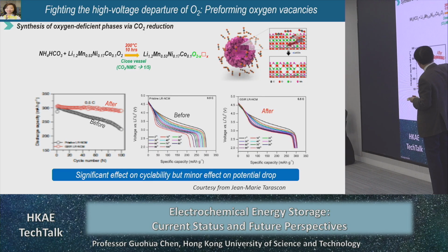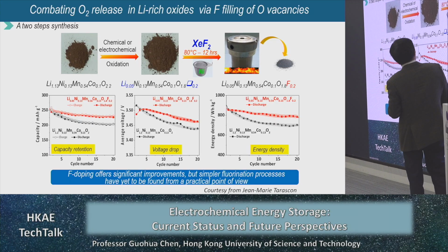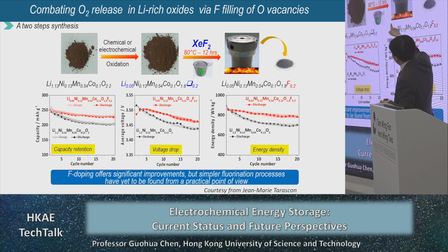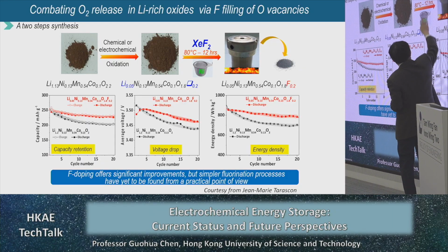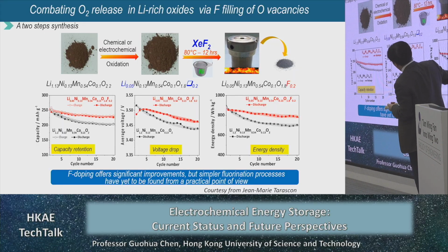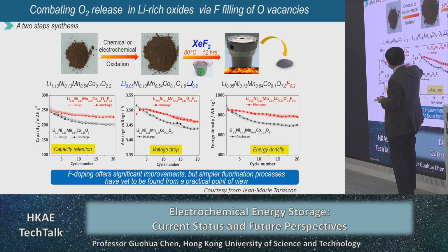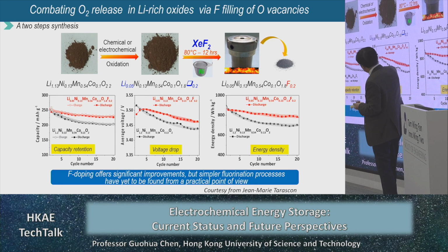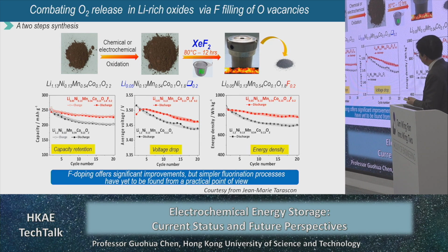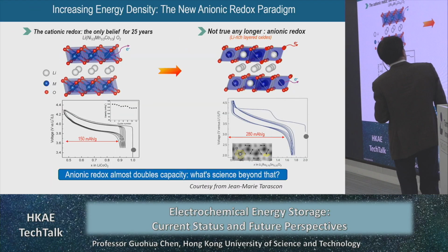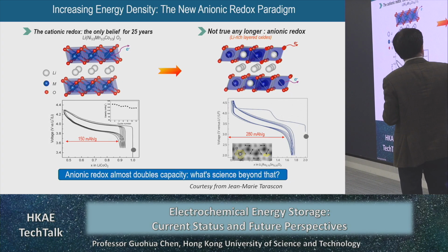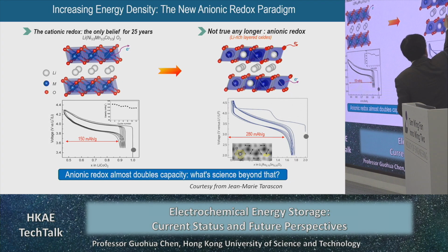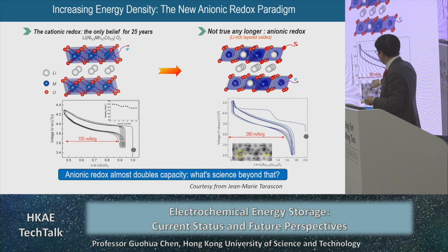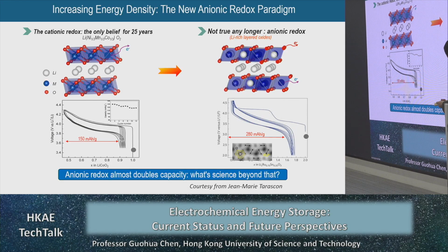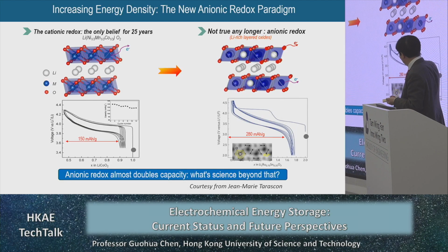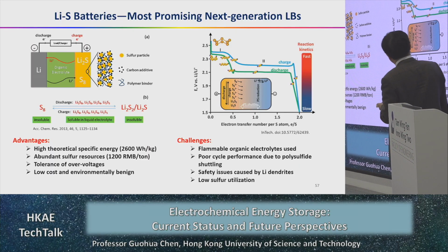So cycling performance, you can see that significant change. Or we could make more doping using fluoride, okay, here. And with the fluoride, this is the work from Jean-Marie Tarascon's group. You can see the change in terms of voltage, capacity, and also energy density, okay? And so next, they're talking about the new anionic redox reaction we mentioned. Anionic redox could also play a role so that we could have a capacity from 150 to 280 milliampere hour per gram, okay? And so this is another,